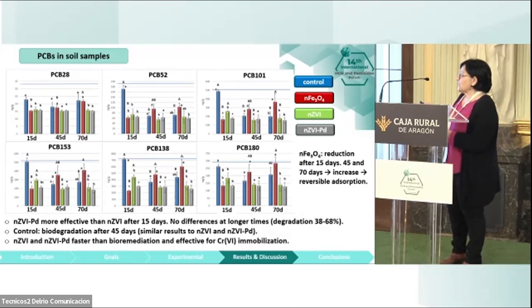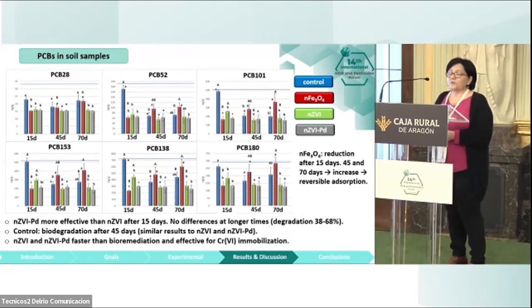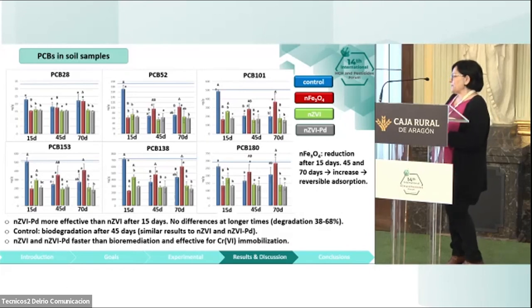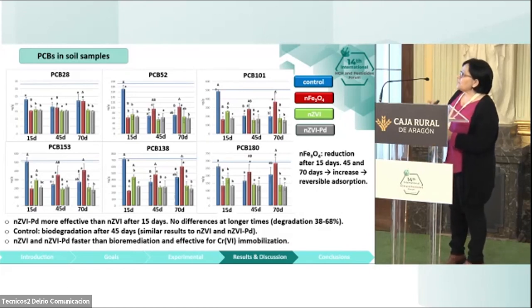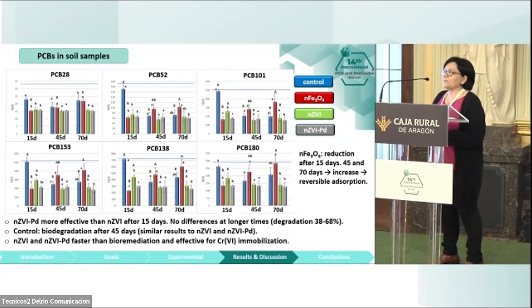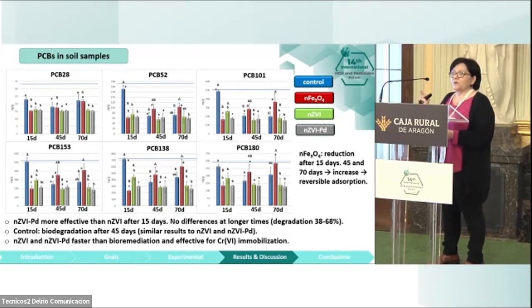In the case of iron nanoparticles, both with palladium or without palladium, here the efficiency is much higher. With palladium, we have to say that this is faster. After 15 days, we can see better results with palladium, but after 45 days or 70 days, the efficiency is just the same. Another interesting thing is that the blue columns, the control columns, didn't have any kind of treatment with nanoparticles, but this also diminishes over time.